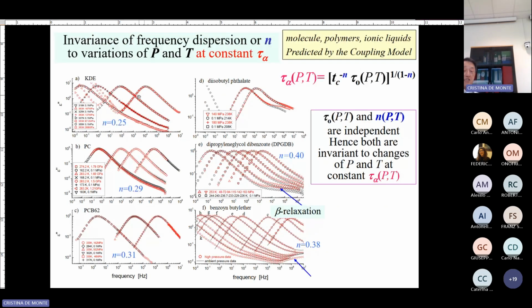So let's look at data. First thing, oh, I forgot to say that. First thing is already amazing when you do an experiment like this typical one. When you do different pressure and temperature combinations, the alpha relaxation peak, you see the peak here, we call it the frequency dispersion. Now, these are different combinations of pressure and temperature. Sorry, it's too small, but you see that there are many different combinations, and they're very different. Sometimes you apply pressure up to 1 gigapascal, which is very high pressure, because normal pressure is 0.1 megapascal. So it is an order of magnitude change. You change the temperature to make the same peak here, but then they superpose. It's beautiful. Now this is also predicted by the coupling model.